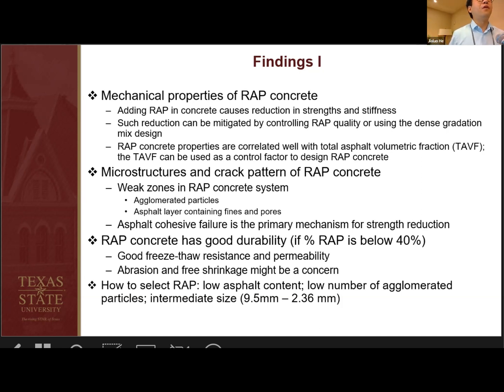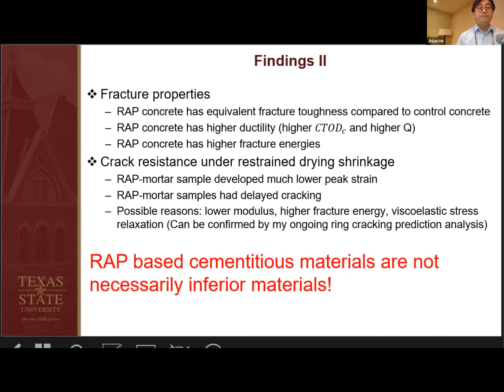We prefer lower asphalt content, but we also have a method to design the RAP concrete with adequate strength based on the asphalt content. Based on the fracture properties, we found RAP concrete has equivalent fracture toughness compared to the control sample. It has higher ductility and higher fracture energies. And for the cracking resistance, we found the RAP mortar sample developed delayed cracking time, and the possible reasons are the lower modulus, the higher fracture energies that we tested, and also viscoelastic stress relaxation.